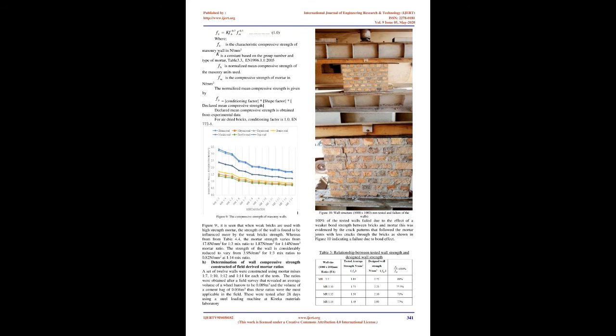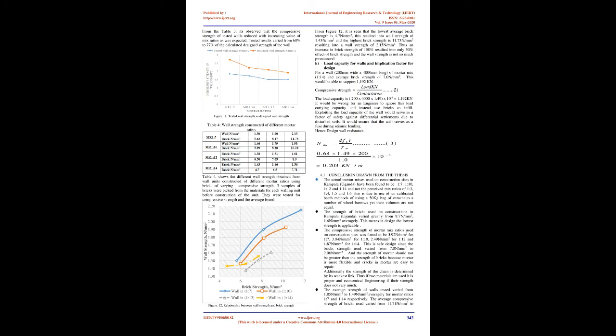For air-dried bricks, the conditioning factor is 1.0. Figure 9, the compressive strength of masonry walls. From Figure 9, it is seen that when weak bricks are used with high-strength mortar, the strength of the wall is found to be influenced more by the weak brick's strength. Whereas from Table 4.4, the mortar strength varies from 17.8 N/mm2 for 1:3 mix ratio to 1.87 N/mm2 for 1:14 mortar ratio, the strength of the wall is considerably reduced to vary from 3.9 N/mm2 for 1:3 mix ratio to 0.82 N/mm2 at 1:14 mix ratio.